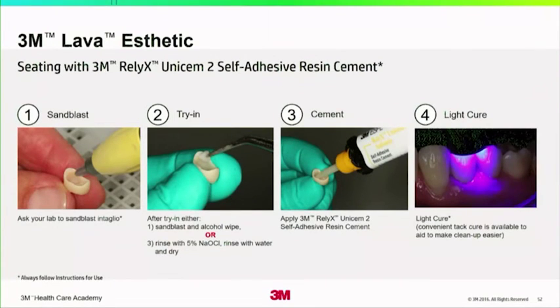This material, Lava Esthetic, you should use a self-adhesive resin cement in nearly all cases. Clean your preparation. Hopefully it's pre-sandblasted. If not, 2-bar pressure. Take your restoration. If you need to rinse it and try it in, rinse it off with sodium hypochlorite, water rinse, dry it. Put your cement in, tack cure, light cure.